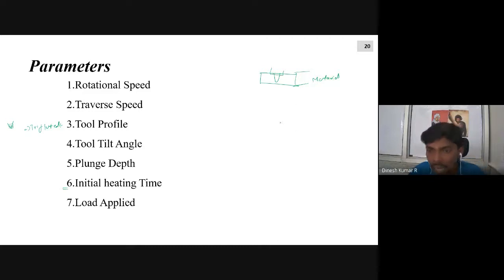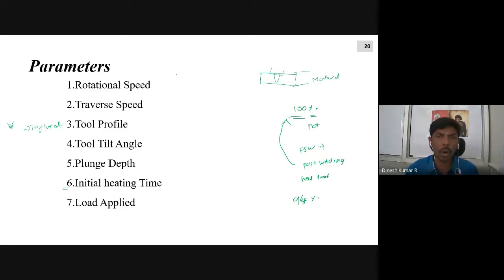So retaining 100% welding efficiency is not at all feasible. If anyone says I am obtaining 100% efficiency by FSW, you can directly say they are blabbering, because this is not going to be a reality. It is possible when you go for post welding heat treatment. When you go for post welding heat treatment, obtaining 100% welding efficiency is possible, but still you can get up to 94 to 95% based on controlling all these process parameters. If you could control all these process parameters in a proper way, the best possible value will be around 94 to 95, when you compare with the fusion welding process,